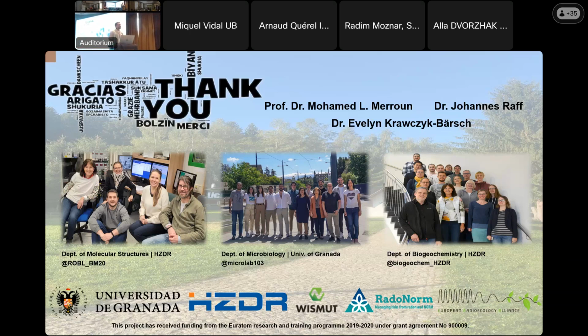Thank you very much for your question, Laureline. Not after 2 or 3 months, but after 1 month, we analyzed the sample by HERFD-XANES. We are waiting to analyze the sample by EXAFS as well, but we measured the uranium-5 again, and the amount of uranium-5 increased. So we could prove the stabilization of the uranium-5 in this case, and probably there is a disproportionation of uranium-4 to uranium-5. Because the uraninite, for example, the uranium-4 percentage decreases, so there is an increase in uranium-6. So probably due to this oxidation, there is an increase in the uranium-5 after 1 month under oxic conditions.